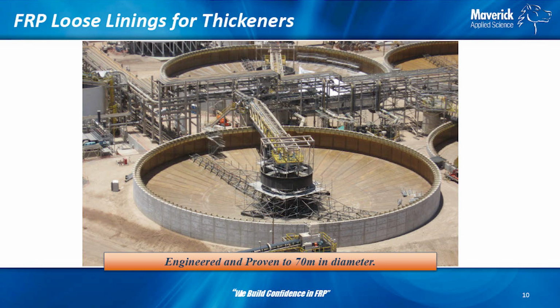So when we talk about loose linings, Kevin showed some photos of this earlier. This is a panel construction basically, and we've seen these done up to about 70 meters. So we're talking very large structures, and they're highly engineered, and you can see the panels there, and you can see the amount of weld. If I was doing that all by hand, it would be a patchwork all the way around. So we basically eliminated probably 70 to 80% of the handwork that goes into this. So we're going to drill down on this a little bit more now.